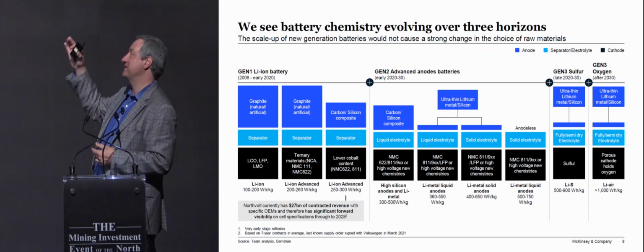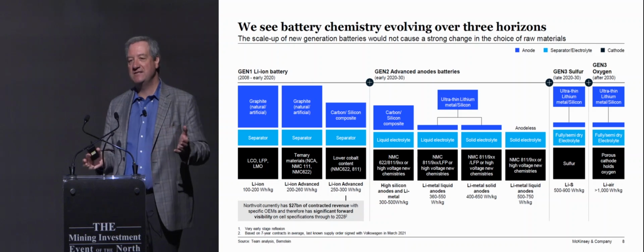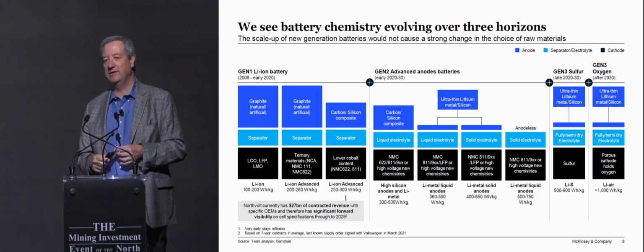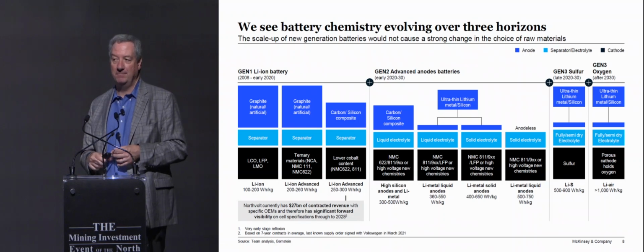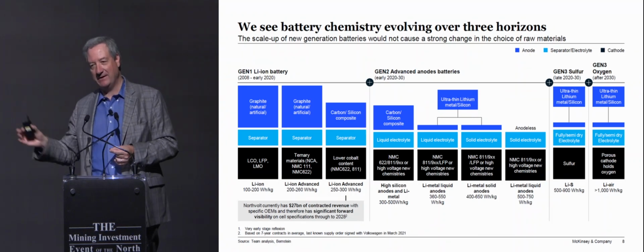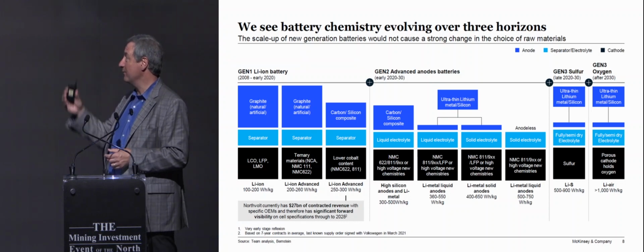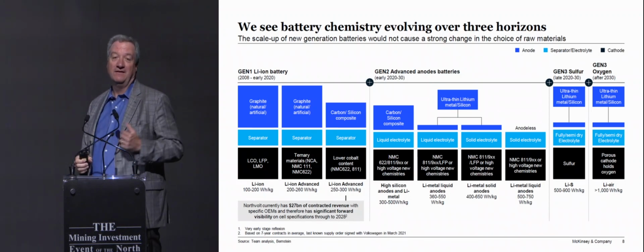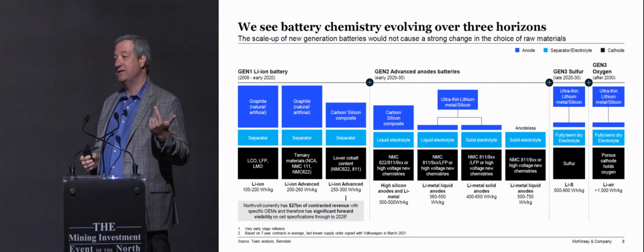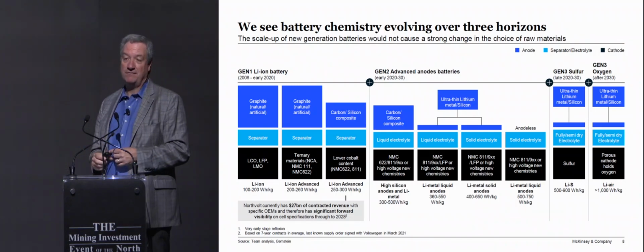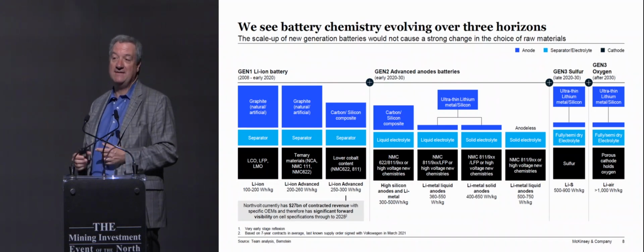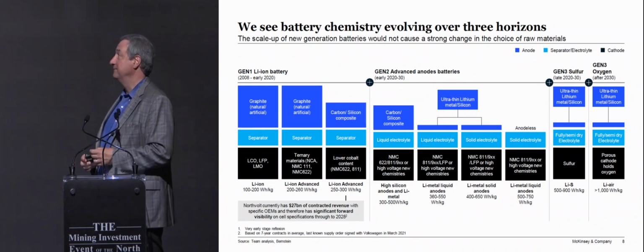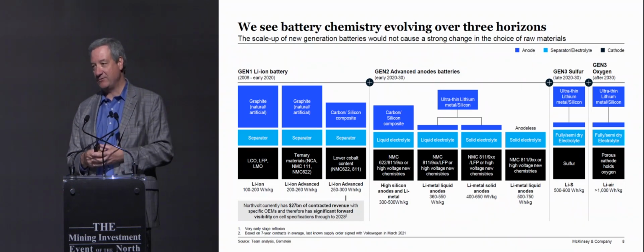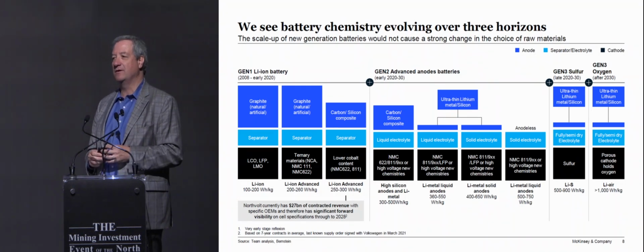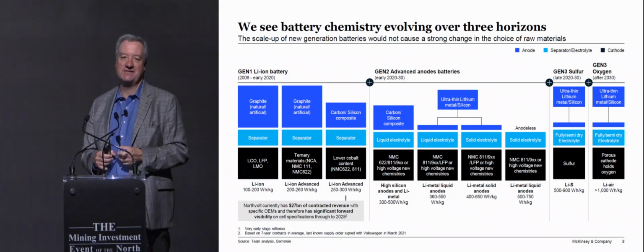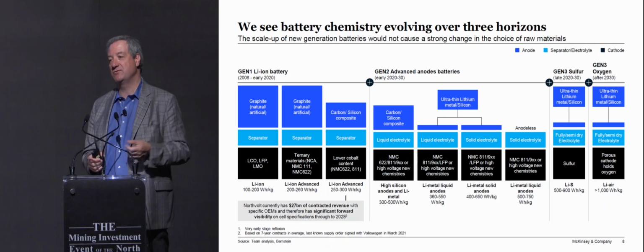They have no cobalt, and so that's quite a bit cheaper. But what you hear in the press today is the move to the anode. Anode today is a graphite material, usually with 3 to 6% silicon added. You'll hear the phrase solid-state battery, which is a horrible phrase, actually. What we're trying to do is change the anode material, and there are two ways to improve it. One is to use silicon. Silicon is far, far lighter than graphite and can hold 10 times the amount of electrons. But silicon has a big problem: when it's filled with electrons, it's like a balloon. It expands 400%, and that expansion and contraction breaks apart the battery. So that's one thing people are trying to solve.